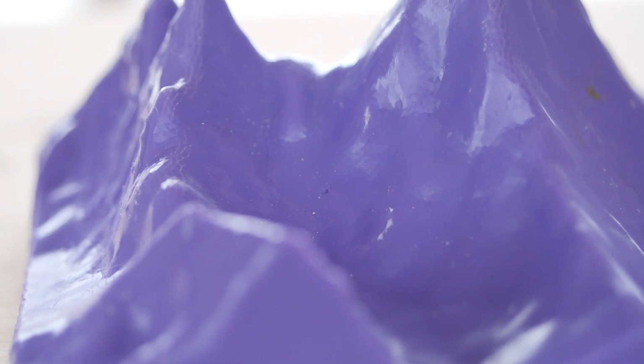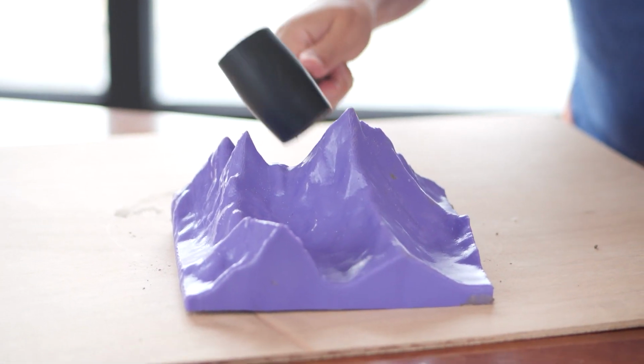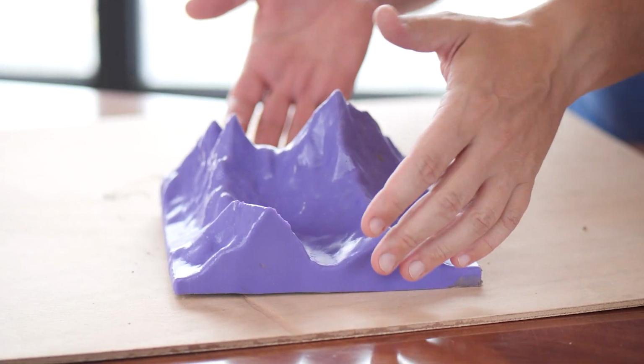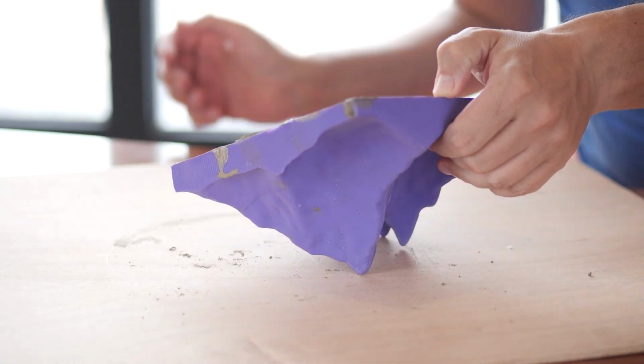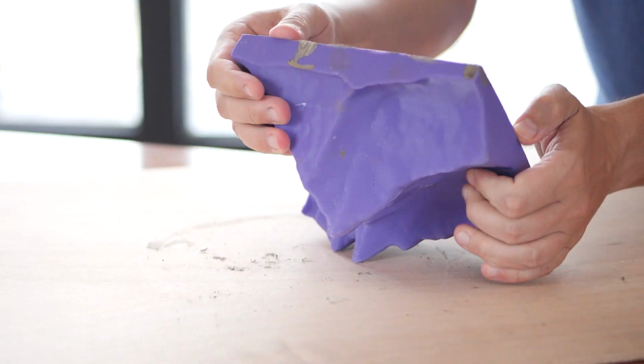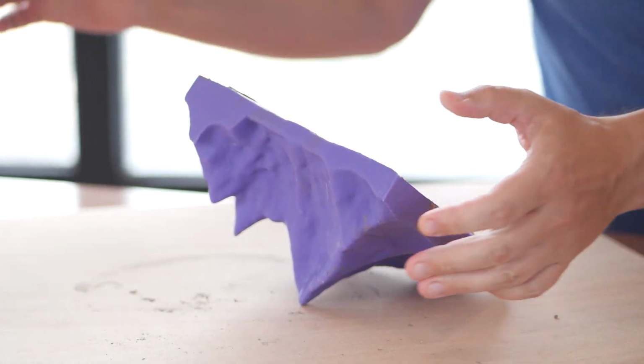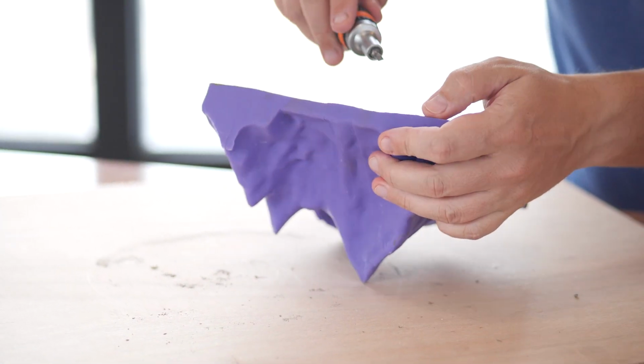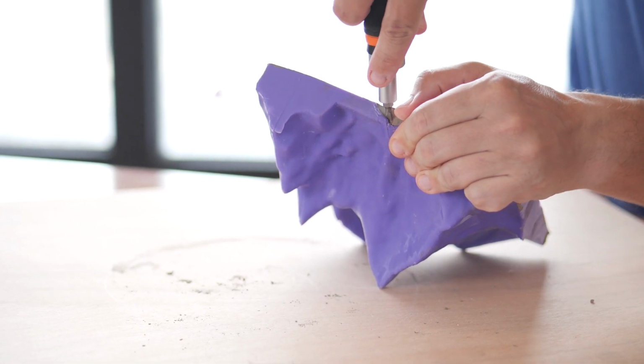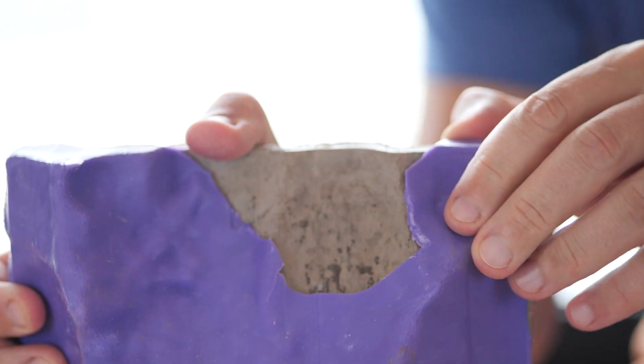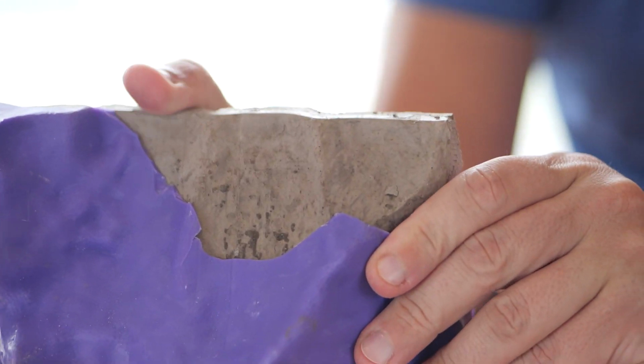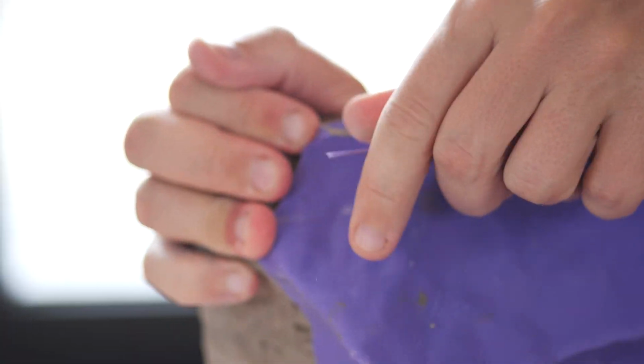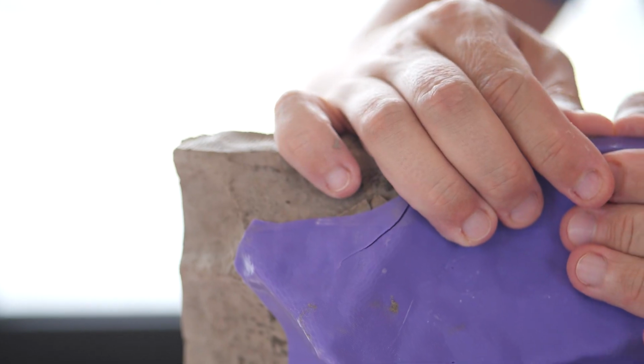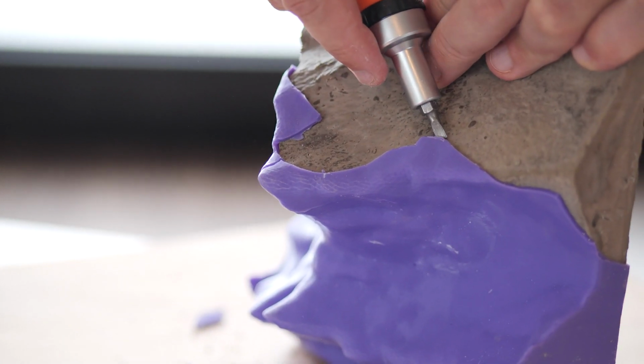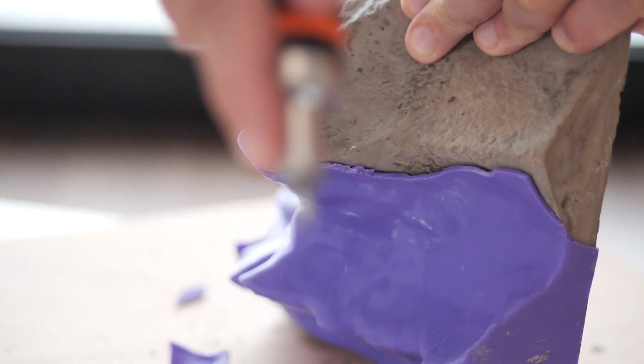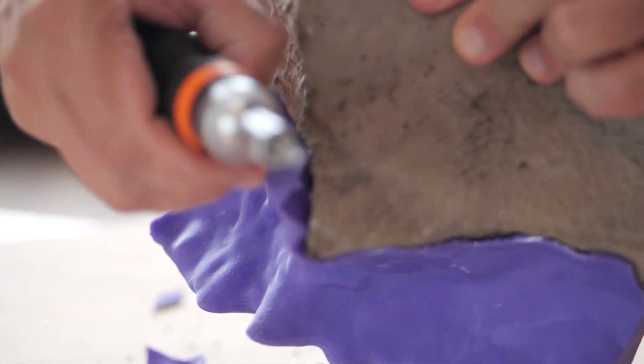After waiting 24 hours, we attempted to extract the concrete model from the mold, but it didn't go as planned. The mold was completely destroyed during the process, and the model itself suffered some damage. This led us to rethink our approach.